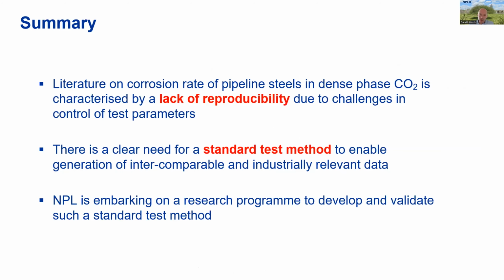So to summarize, we do have a reproducibility problem at the moment in the published open literature on corrosion rate of pipeline steels. This is because it's very difficult to control the conditions in these types of tests. We need a standard test method, and in my organization, NPL, we work on standard test methods. We have a long history of developing standards that can be rolled out to test houses that can generate robust, confident data that allow operators to make decisions, for example, on their CO2 specification and on their material selection. So we've just kicked off a research program, and in fact, we are also involved in the joint industry project that Monica mentioned on the materials corrosion work package, where we're feeding in information on the development of standard test methods and how to control test parameters and generate more reliable results in testing.